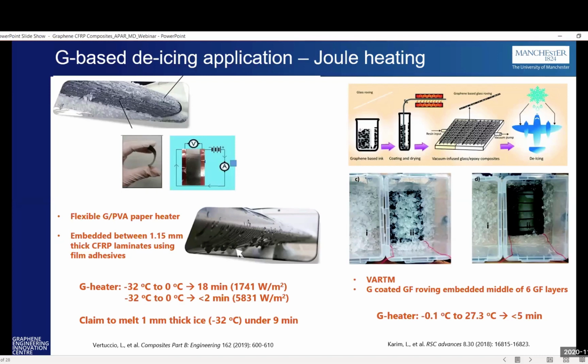So individual glass fiber rovings were coated with graphene-based inks, which were, again, very highly conductive on the surface. And they used the surface conductivity to heat up and work as a heater, basically. And they've seen this heater performs from minus 0.1 degrees to 27 degrees C in less than 5 minutes. So you can see the multifunctional gains that you can obtain apart from just adding graphene for the reinforcement. You can actually develop other applications as well.